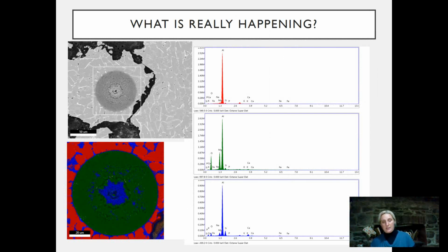How is this happening? Well, what's happening is here. We can see the magnesium actually generating an initial nanocrystalline structure on the fiber. This is magnesium oxide, actually, nanocrystals. What they do is that they fundamentally create and free silicon. So we have an excess of silicon now that tends to go towards the outside, towards the boundary of our fiber.